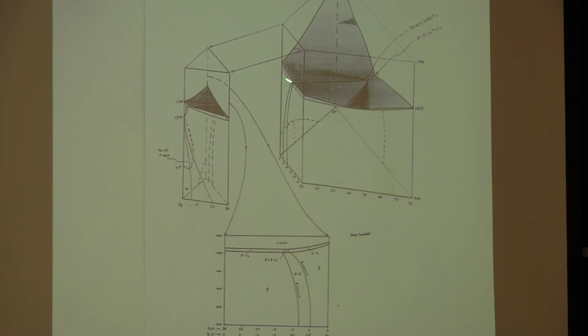If you slice this off basically at 70% iron, which is a typical composition of austenitic stainless steels, then you can look at this surface here, which is exposed by making this slice, and then you've got what we call a pseudo binary phase diagram, and here's where you see that over here you get solidification completely as austenite, whereas over here you get solidification completely as ferrite. And right in this middle region in here is where you get sometimes austenite and ferrite together, and so that's where most of our stainless steels actually fall, is in that region there.